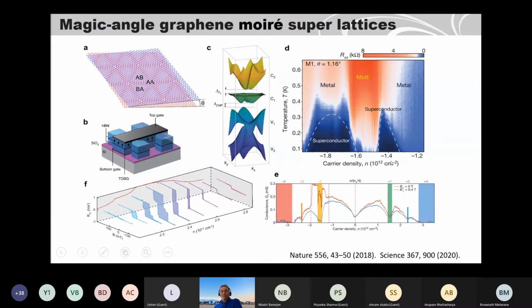And as you change the carrier density, in the same device, you can go from metallic to Mott insulator. And the metal one is called a strange metal. Maybe some of you know in the oxide systems, people talk about that. And also magnetism. This is the anomalous Hall effect, and it's a quantized anomalous Hall effect for some carrier density already. So this is a very tunable system and very interesting to investigate what happens to the spin transport in this system, because you get the strange metal, Mott insulators, superconductors, and also magnetic systems in only graphene bilayers and trilayers also. So there is the recent Science paper, and there are also more papers coming.